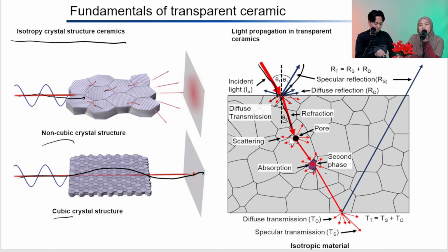And when there is a pore here, see? Oh yeah, pore. Usually we find pores in our materials. Yes, correct. Especially for ceramics, it is very difficult to get a very dense microstructure, so the pores in transparent ceramics should be minimized. And when the light meets the pores, it should be air, right? Yeah, it is air. So the refractive index should be different. Correct. You get it very fast.